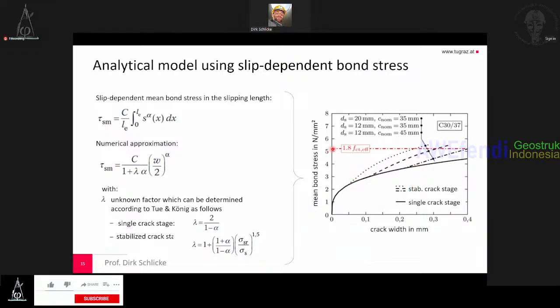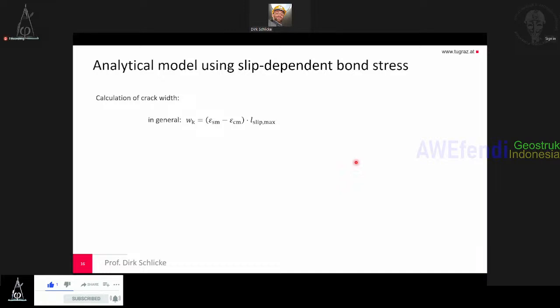What we usually use in the calculations is a constant mean bond stress of 1.8 fctm, and you see, especially in the area where we often want to control the cracks, so between 0.2 and 0.3, it depends significantly on the crack stage whether this is a good approximation or not. And if this crack width gets smaller, it's actually a very bad assumption, what we have in the code. Anyway, in general, we calculate the crack width with the strain difference times the slipping length. And for maximum crack width, we of course use the maximum possible slipping length.